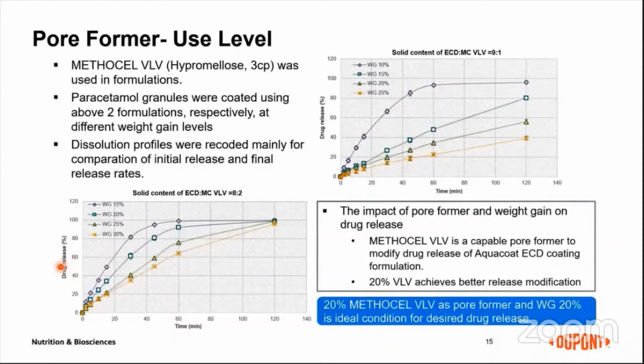The VLV HPMC grade is a capable pore former to modify drug release of Aquacoat ECD coating formulation. So it looks like 20% of VLV can achieve better release modification. So here we can see the 20% of Methocel VLV as pore former, and coating weight gain 20% is the ideal condition for desired drug release.